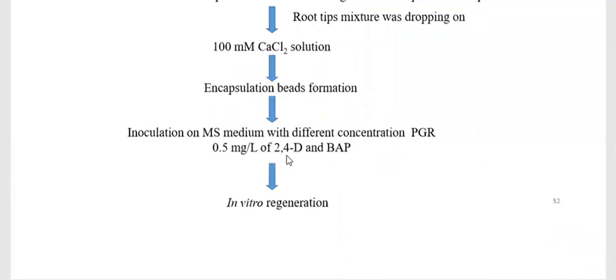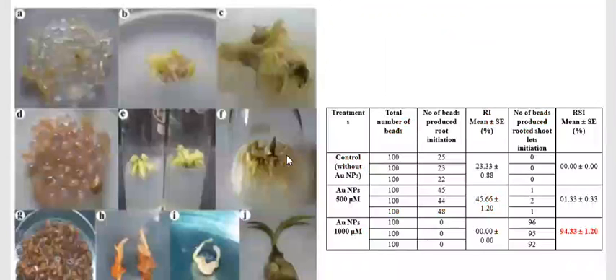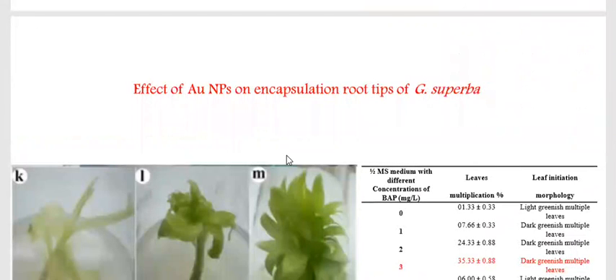impact. Already well known, sodium alginate plus calcium chloride gives calcium alginate beads and sodium chloride. So gold chloride plus MS medium plus 4% sodium alginate is immersed with the 4% Gloriosa root tip explants, and with 100 millimolar calcium chloride, the beads form. With the plant growth regulator, to investigate the regeneration in tissue culture medium, it showed that these are the beads.